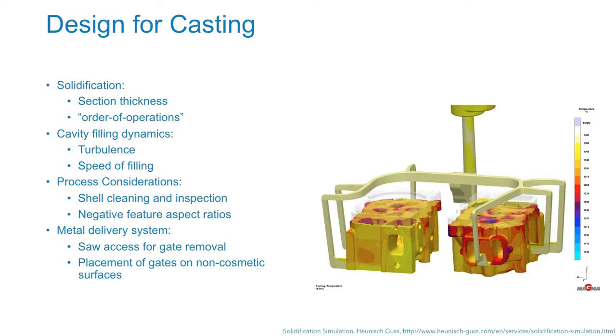Additionally, the casting process itself comes with a lot of its own design constraints. We're working with a process that involves a phase change, so there's a densification that happens, and there's a lot of considerations around fluid flow and heat exchange. So thin features are going to cool more quickly than thicker features. And you likewise want to minimize the turbulence as that metal flows into that cavity, because metal has momentum, and that momentum is going to be transferred to the structure of the mold. We're working with a relatively fragile mold here, so you want to keep that in mind.